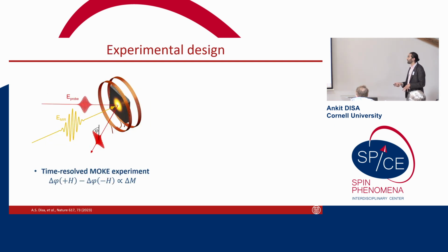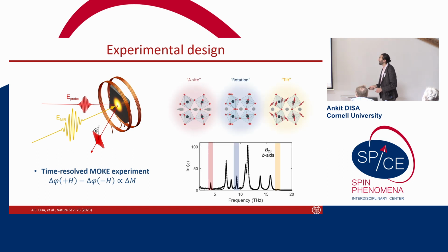And the experiment is quite similar to the one that I showed you in cobalt fluoride, where we essentially pump the lattice with some resonant terahertz mid-IR light pulse, and we probe the magnetization using some magneto-optic effect. In this case, we do it in reflection, so we're using MOKE. And what I'll show you is a MOKE signal, which is proportional to the change in the magnetization of the ferromagnetic yttrium titanate as a function of time.